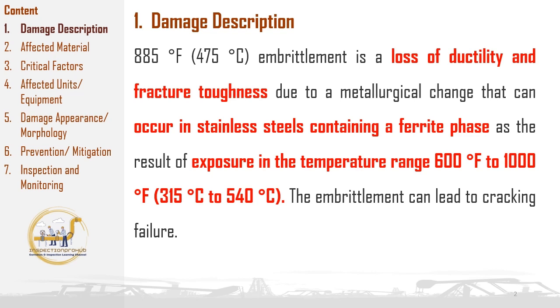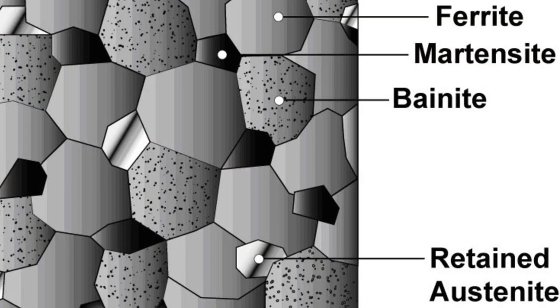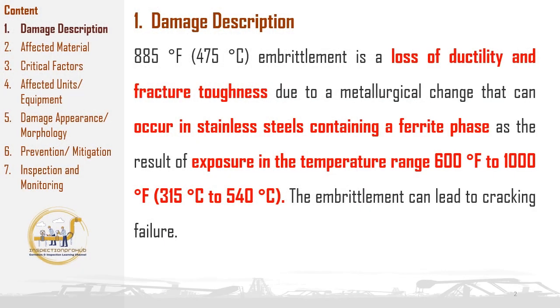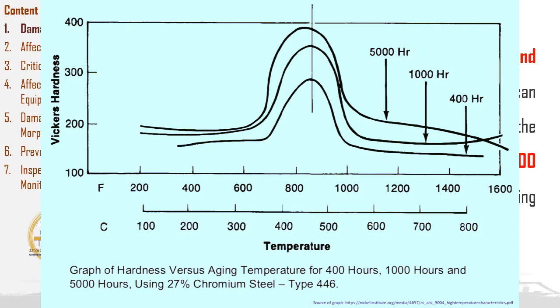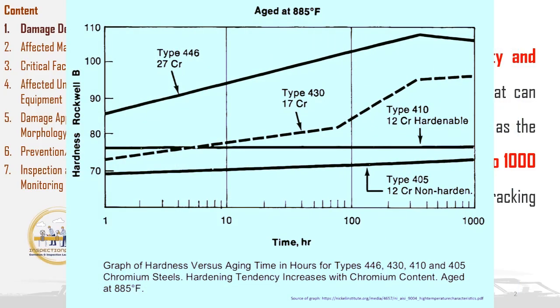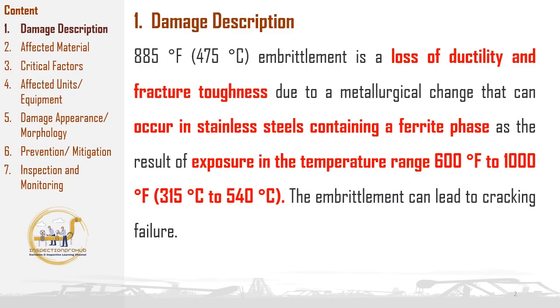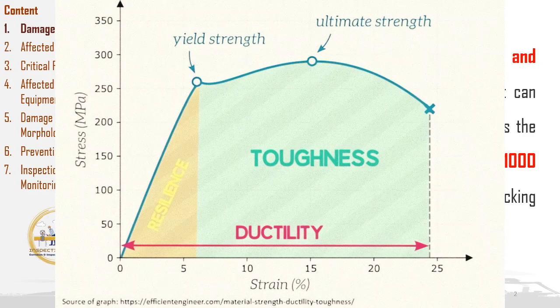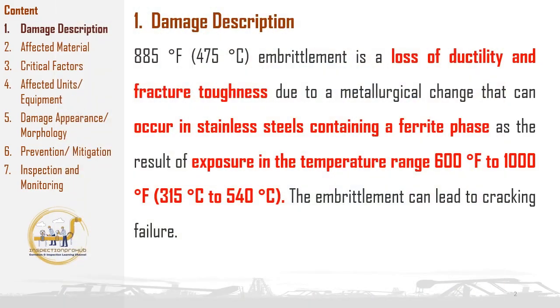885 degrees Fahrenheit embrittlement refers to a phenomenon in stainless steels, particularly those containing a ferrite phase, where the material becomes more brittle and prone to cracking or failure after being exposed to certain temperatures, typically in the range of 600 to 1000 degrees Fahrenheit, or equal to 315 to 540 degrees Celsius. The term embrittlement is used to describe the loss of the metal's ductility and fracture toughness. Why does this happen in ferritic stainless steels?